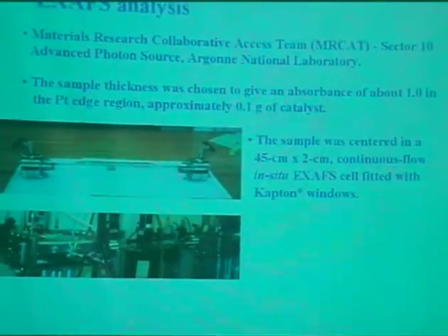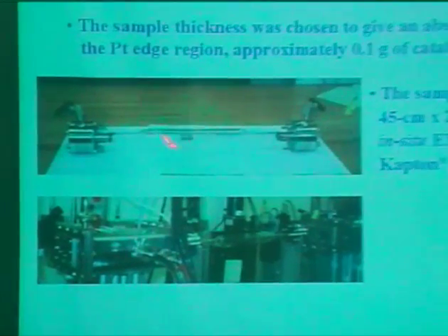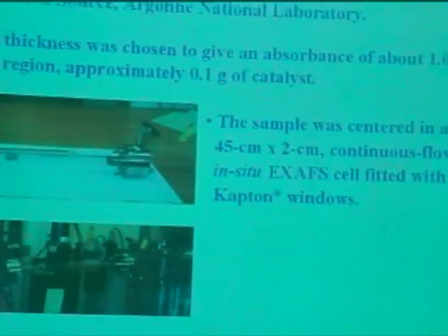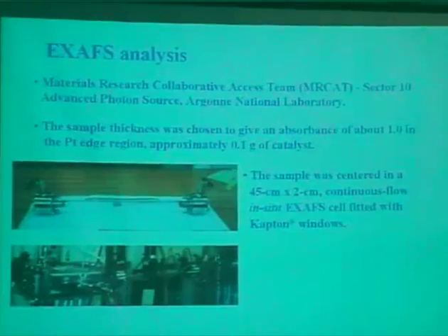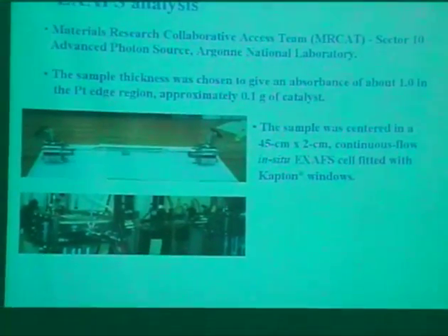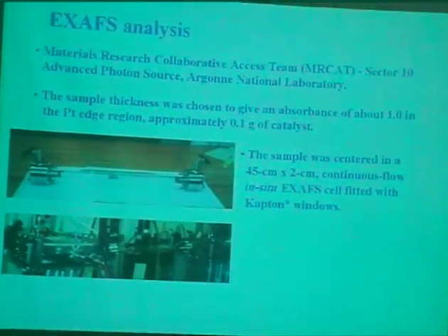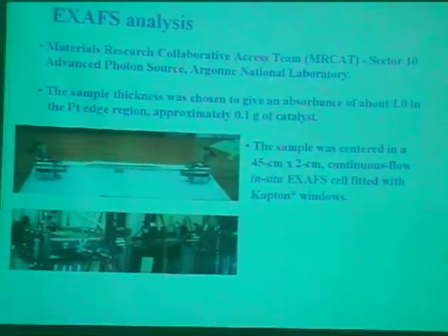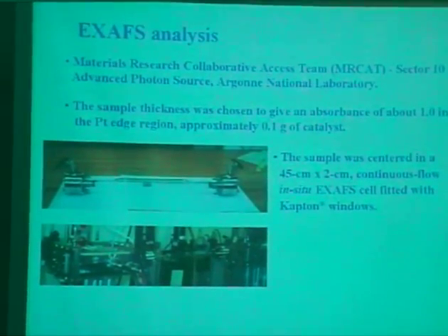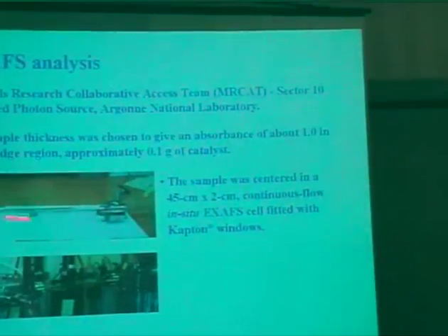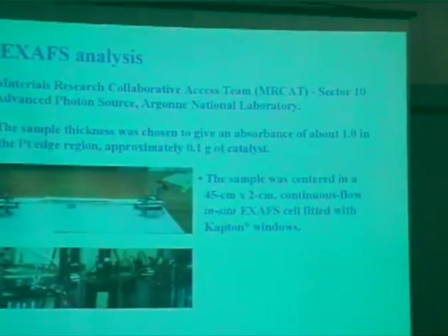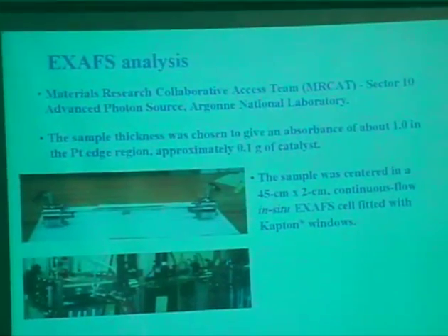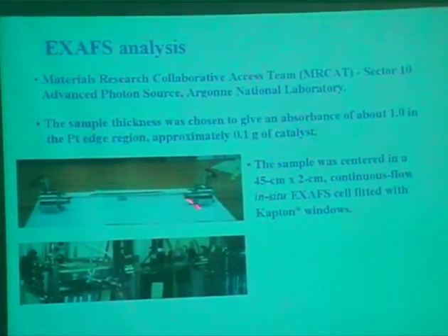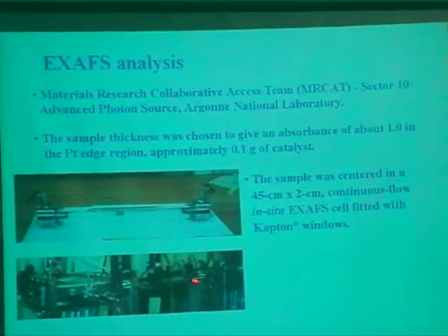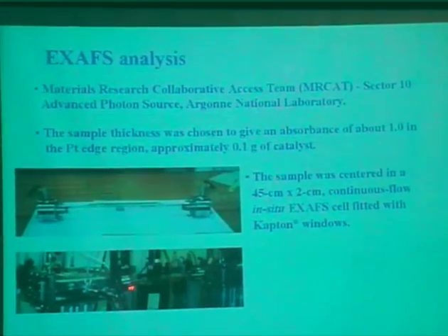All right? An important thing is that the catalyst is there in a little holder, very thin, and we take it, you see two valves here, we take it to a hood, because there are very strict regulations in this national lab, connect it to the system, and we pre-treat it under the same conditions that we have used in our reaction studies. And then we cool it down. So it's not at the same reaction temperature, but the reaction environment, which is what defined the surface with the reaction temperature, was similar, and it was sort of frozen in this system. And then we take this into the facility there.